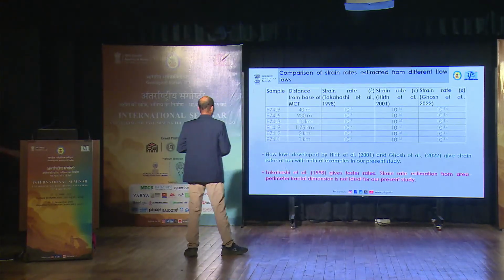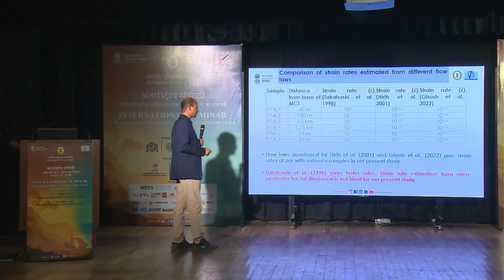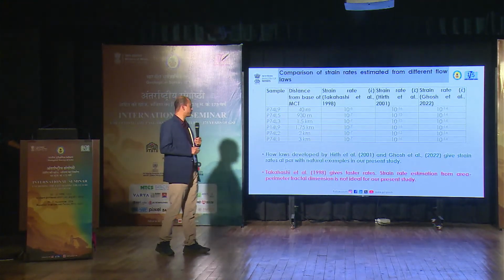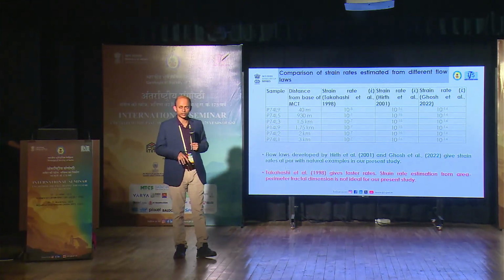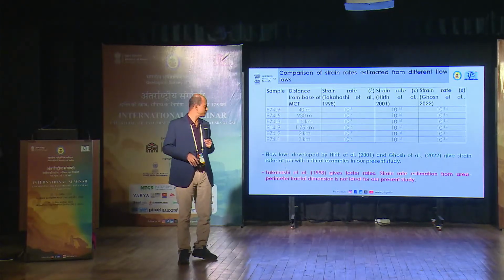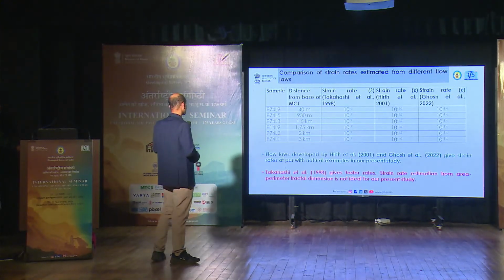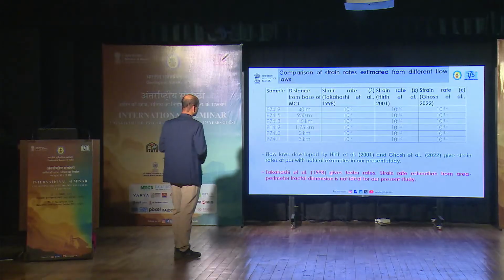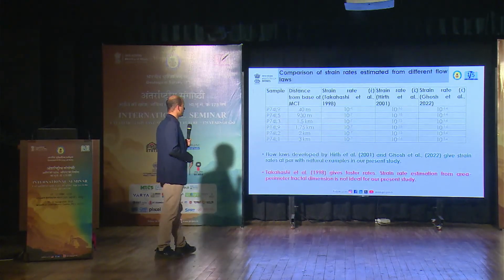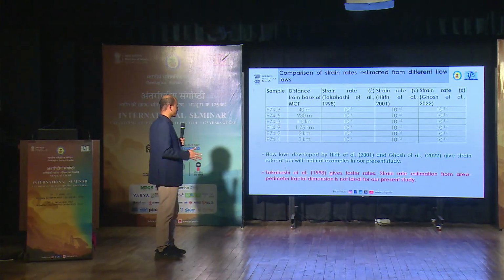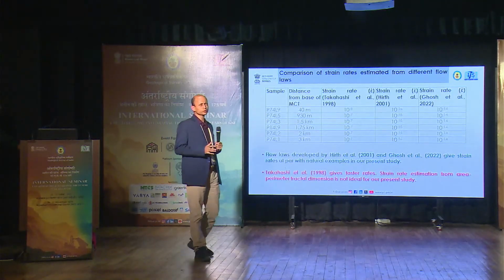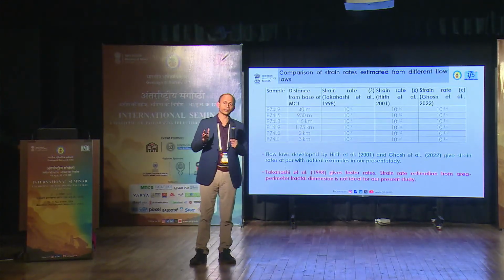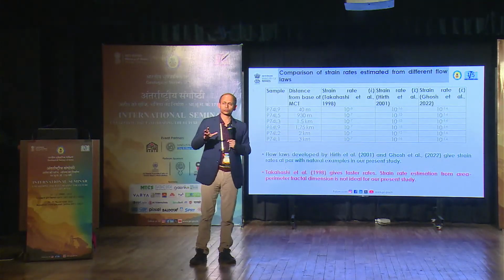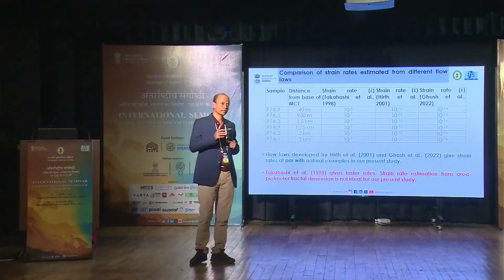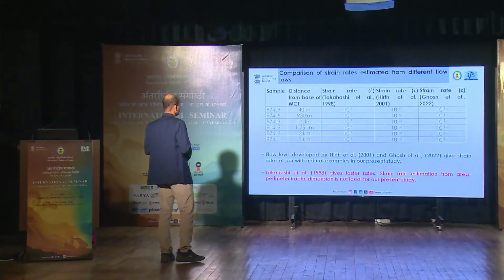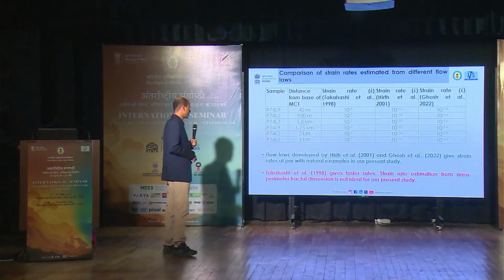Now, what we infer is that the flow laws which have been developed by Hirth et al. and Ghosh et al. are giving us the strain rates during this study which are at par with the natural examples. And further, the Takahashi et al. area perimeter based parameter flow law gives us faster rates. What we infer is that because of the higher temperature within the MCT zone, perhaps that's why the fractal based flow law is not giving us consistent results.